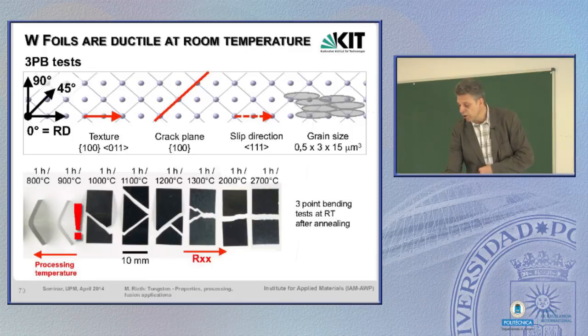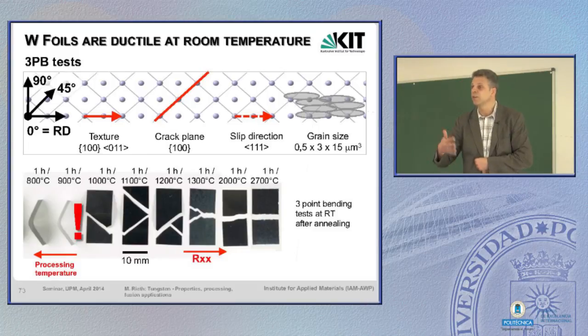The grains are oriented in a 011 direction, in a 100 planes. And if you heat treat this foil up to 900 C, after heating it up to 900 C and cooling it down, nothing happens inside the material.